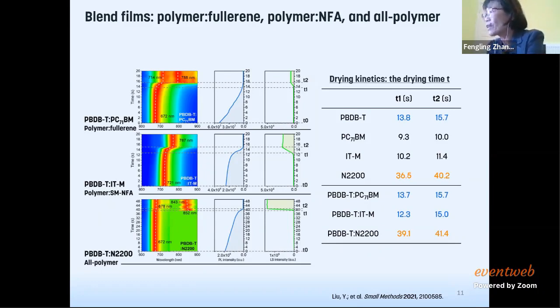For the small molecules, the time is closer to the donor, but for the polymer acceptors, it's dominated by the acceptor. So with this information, we know which one plays the key role here. If polymer blend, we also check the molecular weight. So the conclusion from this study is that the high molecular weight dominates the drying process. So this is the conclusion from this part of the work. This work was published this year. If you're interested in more details, you can read the whole paper. Also there is some supporting information there.